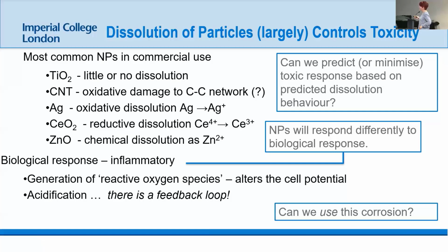And so these are the most common nanoparticles by bulk volume that are currently being used. And if I asked you how any of those particles were going to dissolve, you could probably all tell me this, right? So TiO2 is not going to do very much in terms of dissolution, and it turns out it's not very toxic. Carbon nanotubes don't really dissolve, but you can get oxidative damage of the framework, and that can cause some damage. Silver, that dissolves oxidatively. Ceria, that dissolves reductively, right? The cerium-3 is more soluble than the cerium-4. Zinc oxide, that doesn't need any electrochemistry, that's just a chemical transformation.